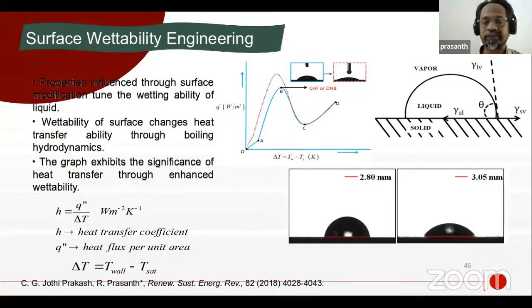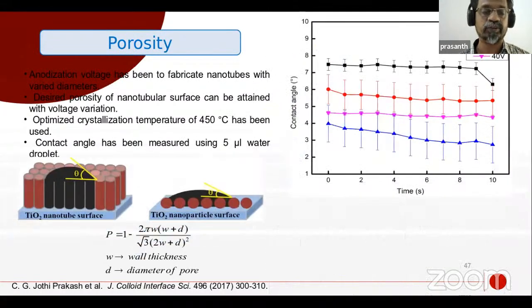And on this tubular surface, after heating and making the bubble, you can get another layer, the wetting layer, that will easily flow. And you can change the bubbling mechanism, the nucleation. I will show some videos, if time permits, of the changed boiling mechanism in the structure. By changing the tube geometry, you can change the wettability of the surface, because you have two different models of changing the wettability of the surface.